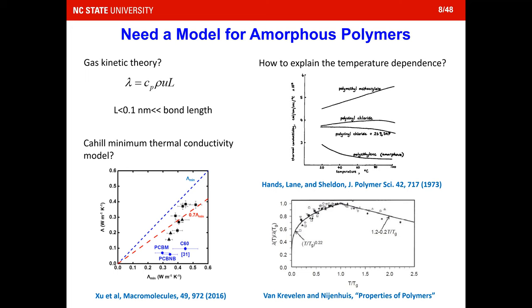We also found that by measuring quite a few amorphous polymer films, the minimal thermal conductivity model he proposed actually overestimated thermal conductivity in these macromolecules. And in addition, there are a lot of different temperature dependences in amorphous polymers that are not able to be explained by gas kinetic theory or the minimal thermal conductivity model or any kind of model. For example, amorphous polyethylene will decrease thermal conductivity with increasing temperature, while other types of polymers will have an increase.